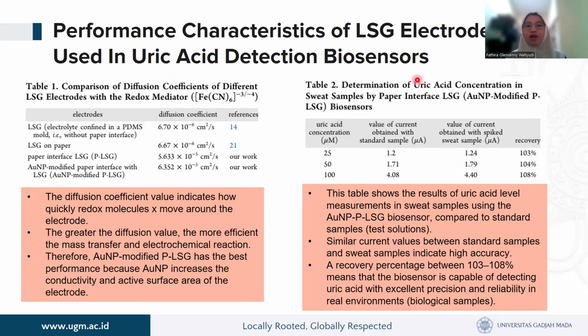Table 2 shows us the determination of uric acid concentration in sweat samples by paper interface LSG, AuNP modified PLSG biosensors. This table shows the results of uric acid level measurements in sweat samples using the AuNP PLSG biosensor compared to standard sample or test solutions. Similar current values between standard samples and sweat samples indicate high accuracy. A recovery percentage between 103 until 108% means that the biosensor is capable of detecting uric acid with excellent precision and reliability in real environments or biological samples.